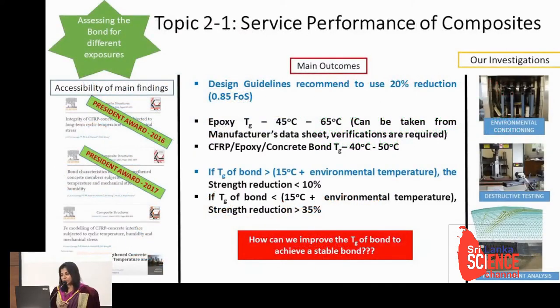So we tested a series of specimens under different environmental conditions using accelerated testing. It covers all the weather fluctuations in the different parts of the world. And also, we could develop a material degradation model. It can predict the degradation with respect to the environmental exposure. So actually we found, normally the Tg, that means glass transition temperature, of epoxy adhesive is 45 to 65 degrees, and you can find it in the manufacturer's data sheet. But the Tg of the bond is slightly lesser than the adhesive, around 40 to 50 degrees.